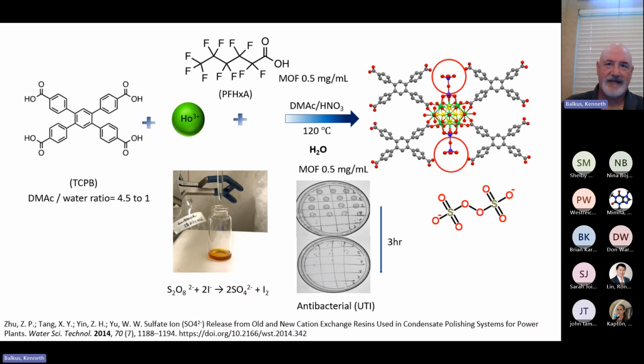And this is one of those weird cases where you end up with this structure. And again, this is a perfluorohexanoic acid cluster that's bridged by persulfate. And you can show that it's definitely persulfate. This is the old iodide test where you mix it and it forms iodine, turns brown. It's also antibacterial. And here's just an example. This is an E. coli. And you can see after 3 hours, just about all the bacteria are destroyed.